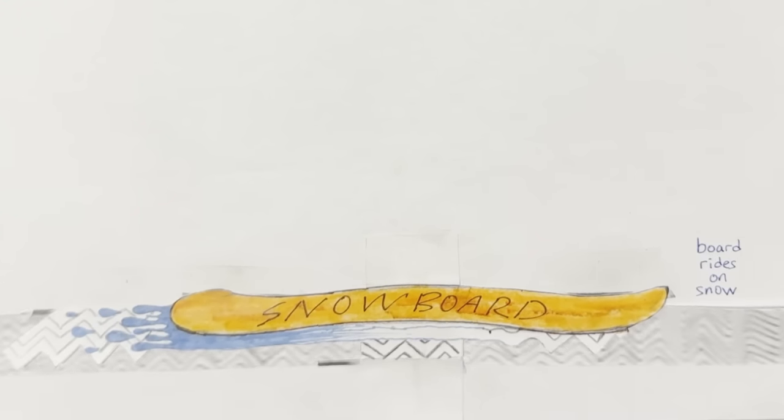What happens if you keep an iron on one spot for too long? The P-TEX base directly under the iron will greatly expand compared to the surrounding base, causing bubbling, warping, and discoloration. This is extremely hard to fix and sometimes can completely ruin a board, so don't leave your heated iron on the board in the same place for more than 10 seconds at a time. To check if you're overheating your base — after passing your iron over the top of the board a few times, touch the top sheet. If it feels slightly warm, that's good. If it feels extremely warm or too hot, you're overdoing it and will soon damage your base. If your iron starts smoking when you turn it on, it's because of remaining wax from the last wax job melting. Remember to use the proper temperature for the type of wax you're using.